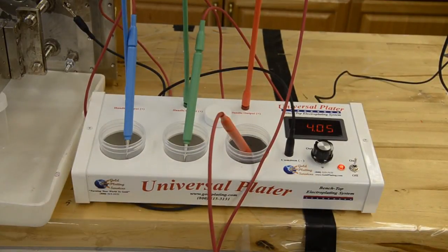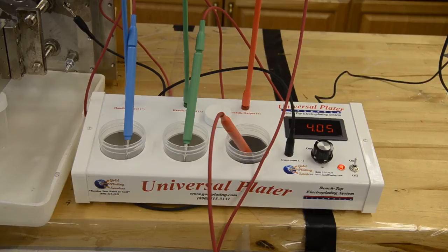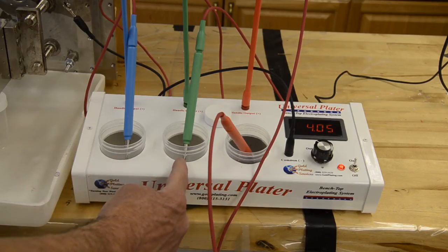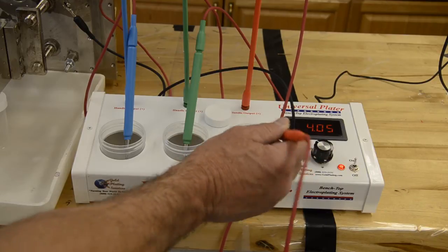Now to properly prepare the electroless nickel for gold plating, we set the first plating beaker up with an electro cleaner solution, the second with a surface activator, and the third with the gold.